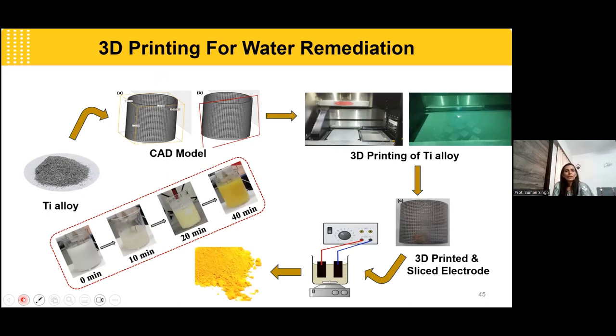So we tried electrochemical synthesis of this graphitic carbon nitride, where that paper used a platinum electrode. But since platinum adds cost, we decided to replace it with a 3D printed titanium electrode. We printed it in circular form and then sliced it in between to use semicircle electrodes. With this, we synthesized graphitic carbon nitride, and we used it for water remediation. Next, please.